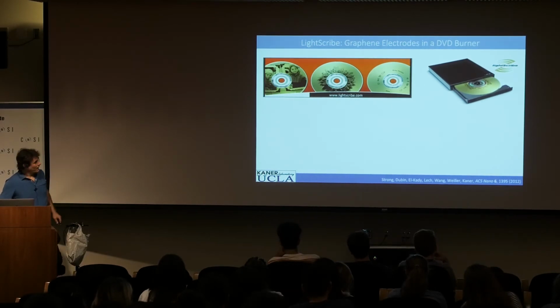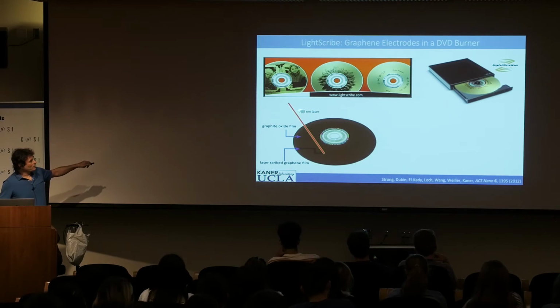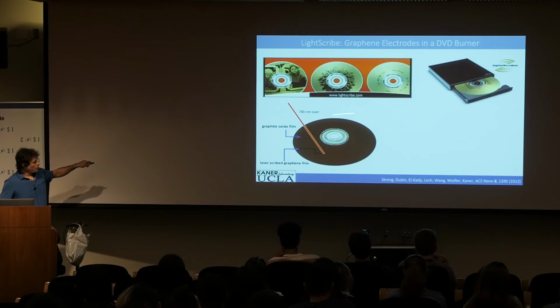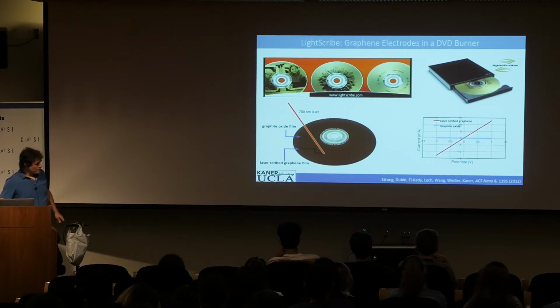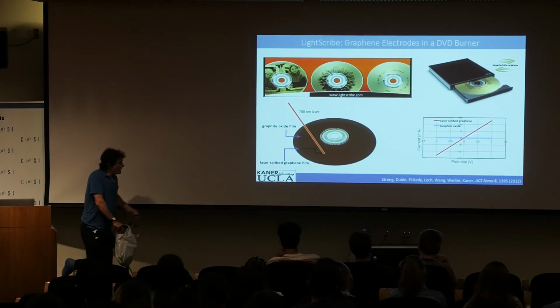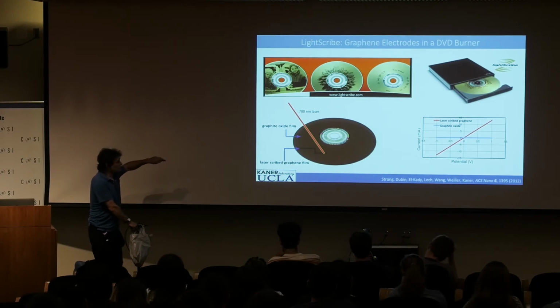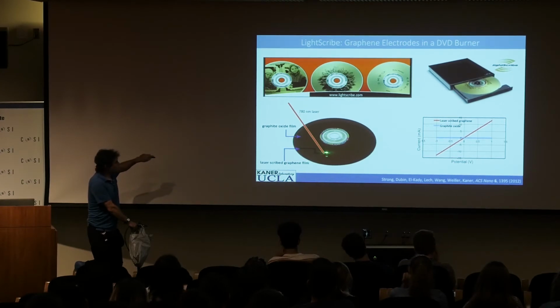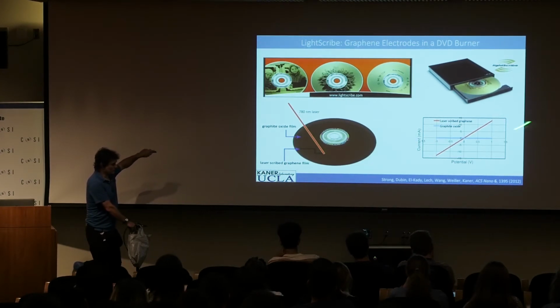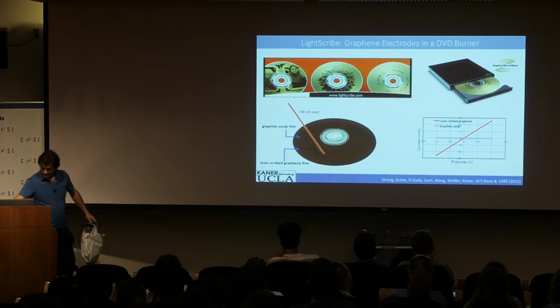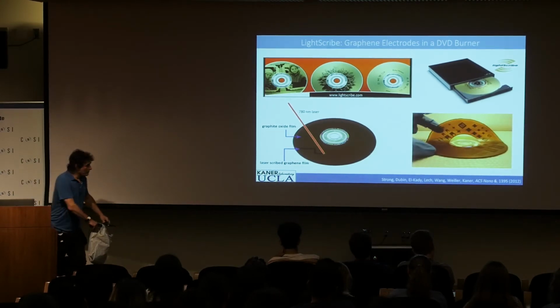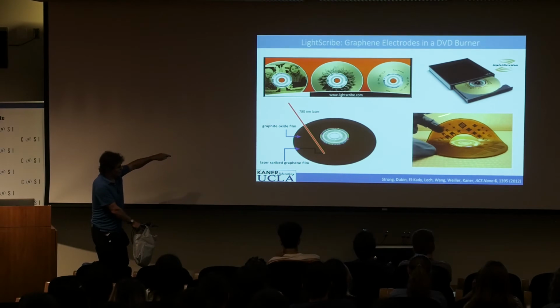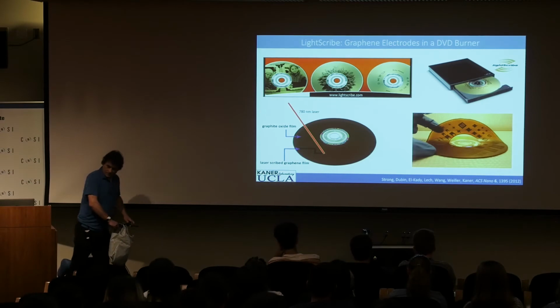You put it in your computer stack, and it consists of a 780 nanometer laser and a magnifying glass, plus a computer program that can raster any image you want. So we simply do this, and this is, again, a current voltage curve, and this just shows that the graphene oxide, the golden stuff, is insulating. And as soon as we hit it with a laser, we convert it to graphene, it becomes conductive. Okay, now, as I said, you can make any pattern you want. So here's, on plastic, we have the graphene oxide, the insulating orange-brown stuff, and we make all sorts of interesting patterns.